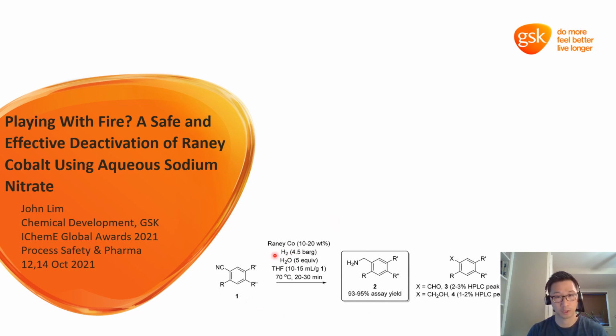Quite a bit of screening went into identifying Raney cobalt as the ideal catalyst for this transformation. Now, because 2 is taken through 3 more stages of chemistry before the API step, it's imperative that we have a clean reaction profile in this reduction, which is what Raney cobalt gives us. However, with any heterogeneous catalytic reaction, there's a filtration involved, and thus there's an inherent risk if that catalyst bed were to run dry.